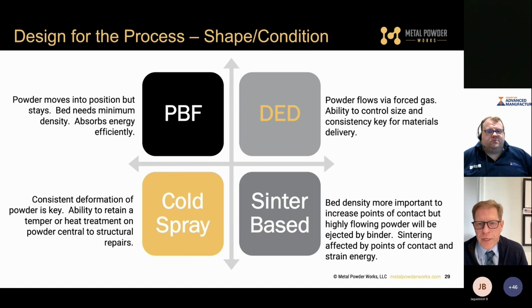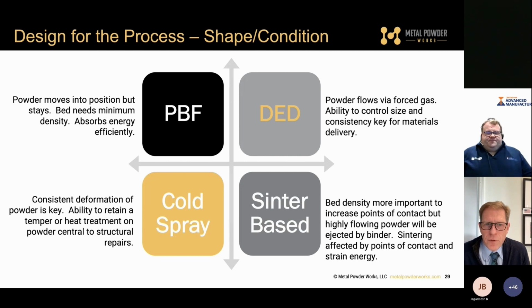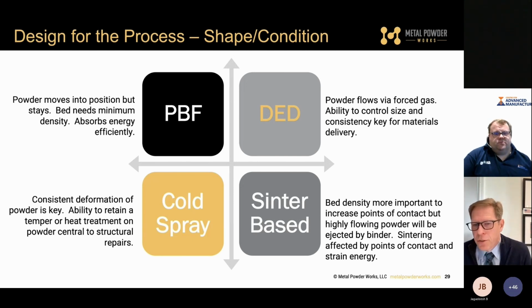And it needs to absorb energy efficiently. We need not to reflect the laser light away, because, again, thinking as a materials engineer, if you're dumping more and more energy into my material just to get it to absorb the heat and melt, then once it's liquid, you're going to drive off, ruin my metallurgy that we've taken great pains to give you. And then you're going to create additional residual stress considerations.